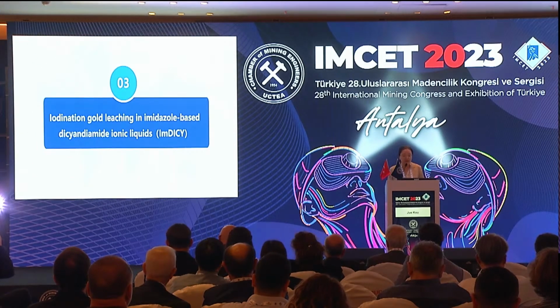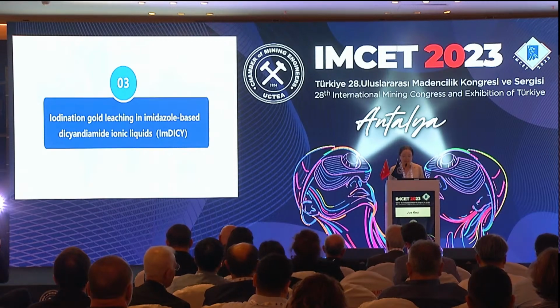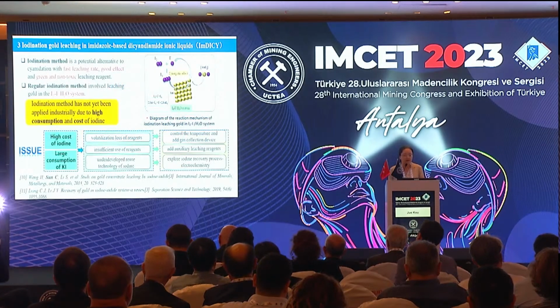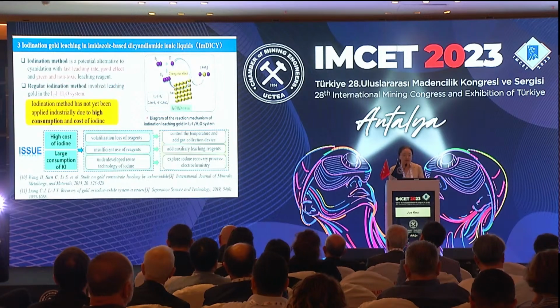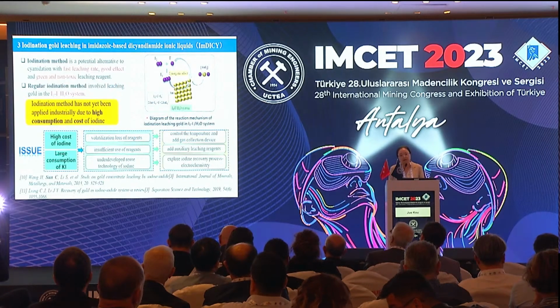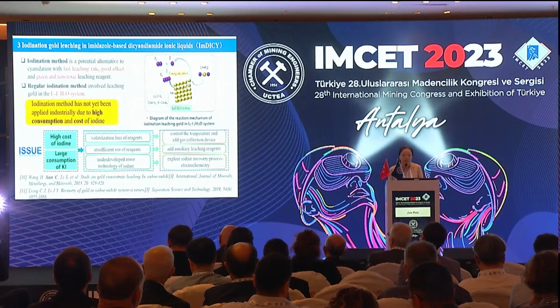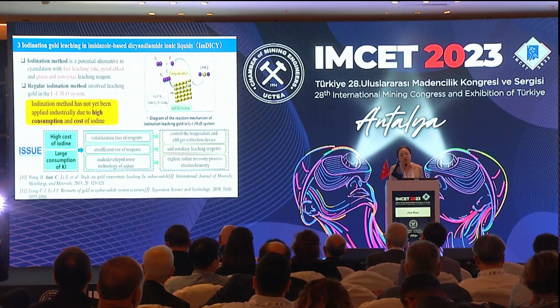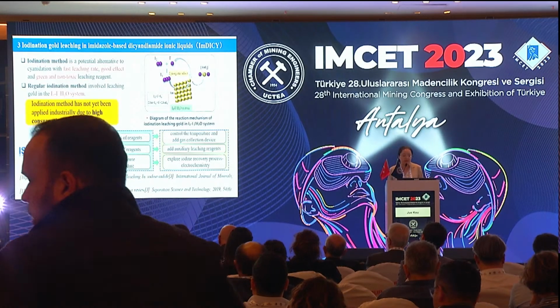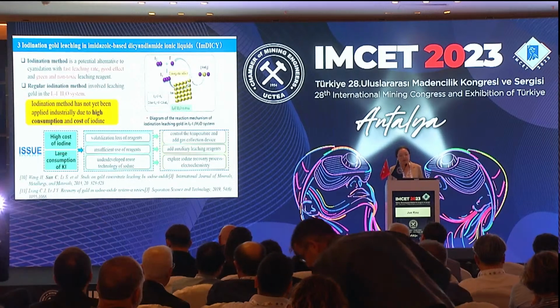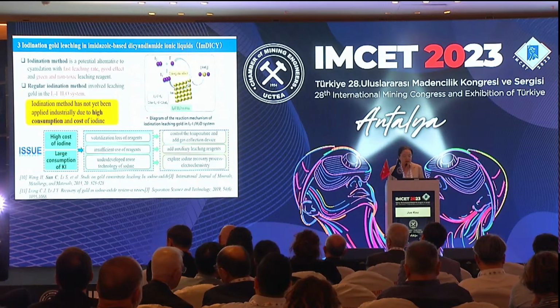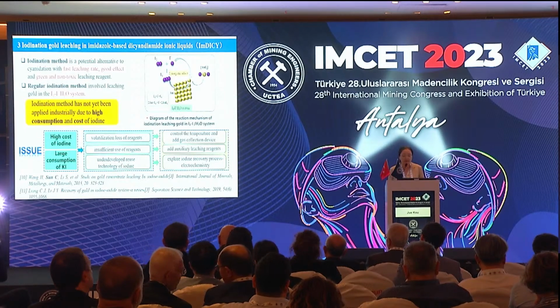And the third part is about iodination gold leaching in imidazole-based dicyandiamide ionic liquids (ImDICY). Iodination leaching is already demonstrated to have a good performance in gold leaching with both raw ore and e-wastes, and some other materials containing gold and some precious metals, because the iodination method has a fast leaching rate and a good effect because of the strong bond between the iodine and gold.